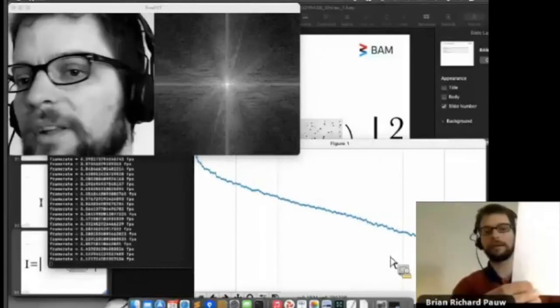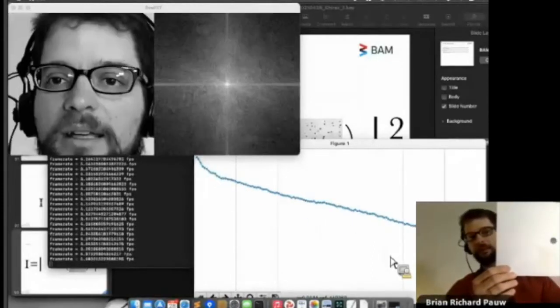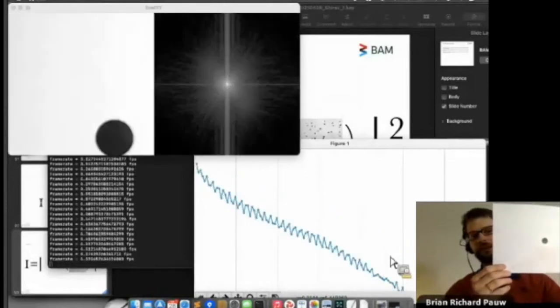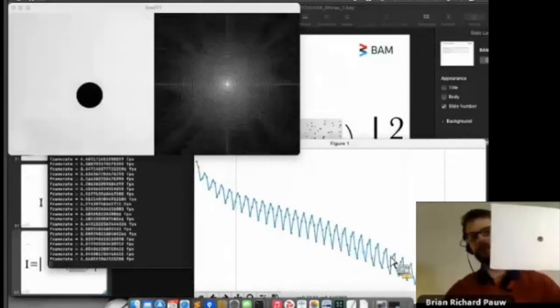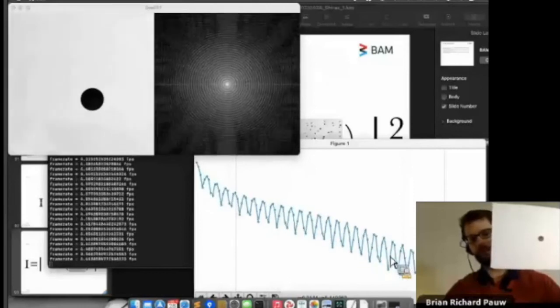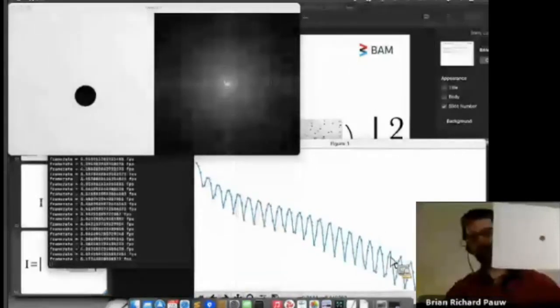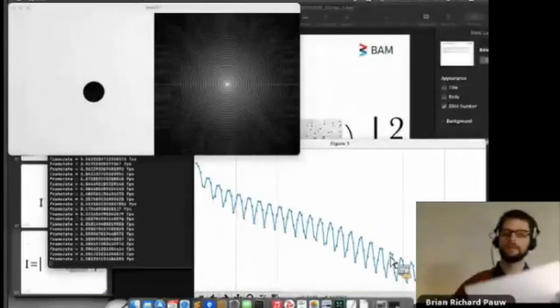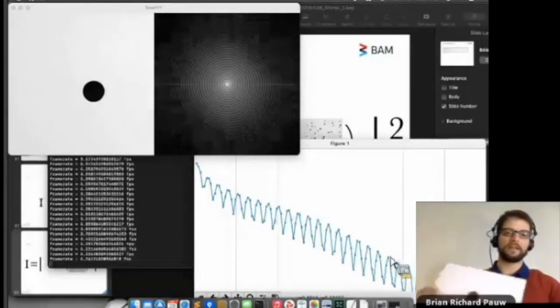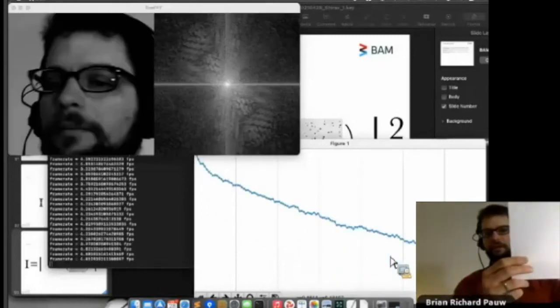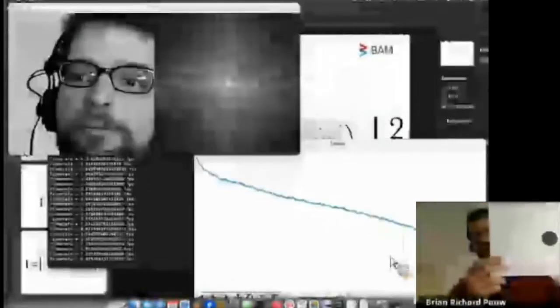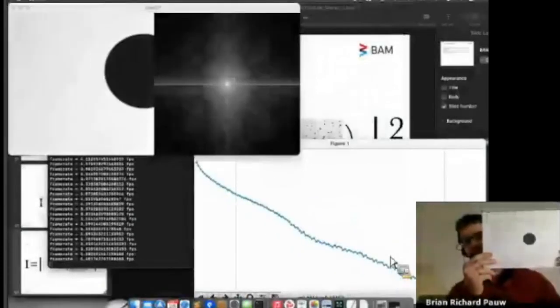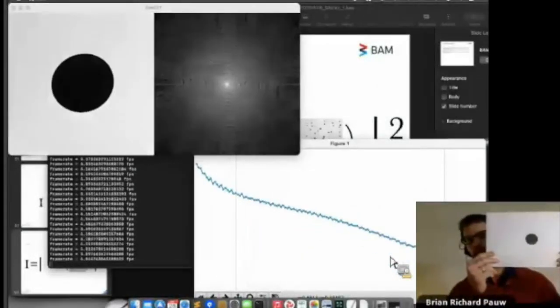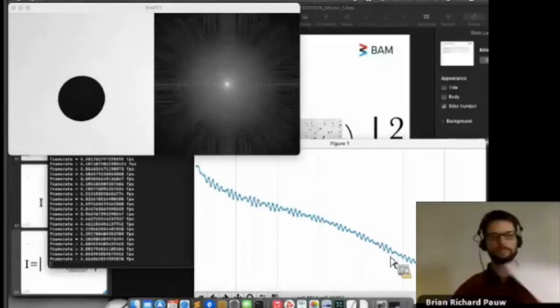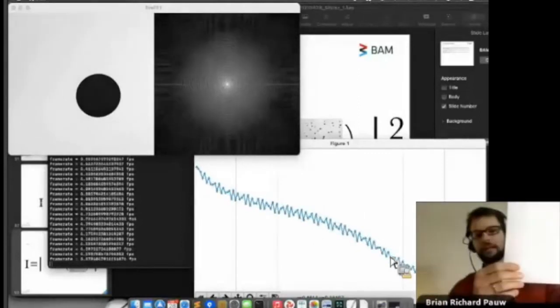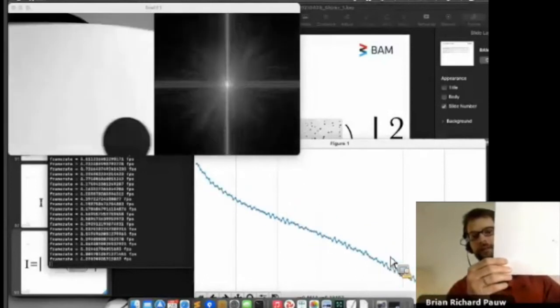So I can show you what happens if I have spherical scatterers. You see, we have these very nice oscillations of these spherical scatterers, which show up as very good features in our scattering pattern. As you now know, if I have a larger structure, these features shift to smaller angles. So I need to move this pretty far away. You get very high frequency oscillations over here. And if I have smaller objects, these things move to wider angles.